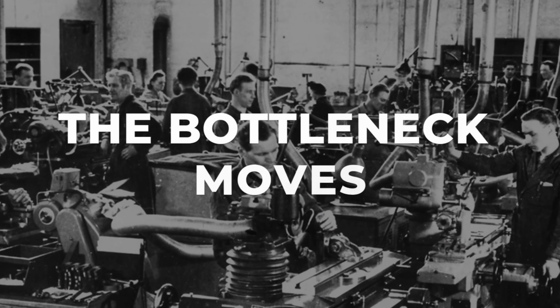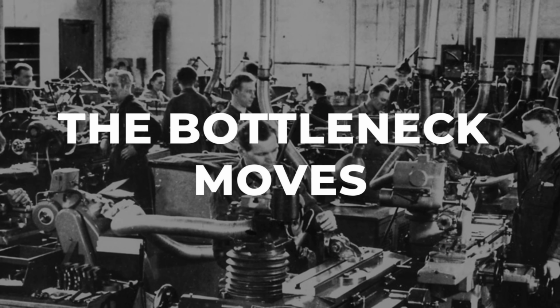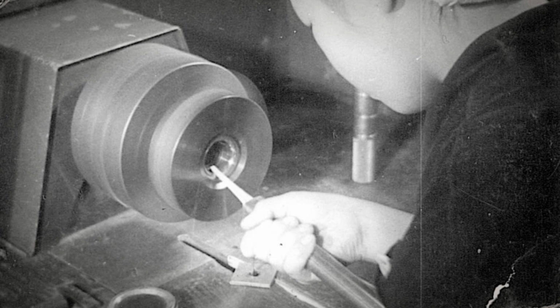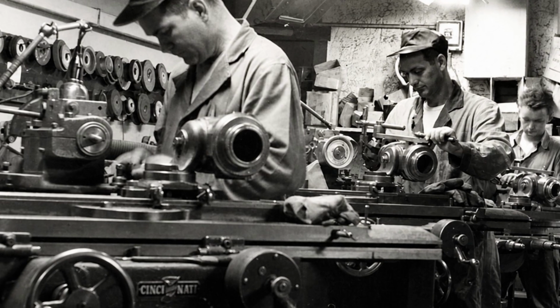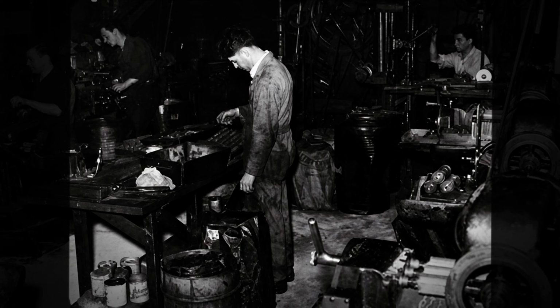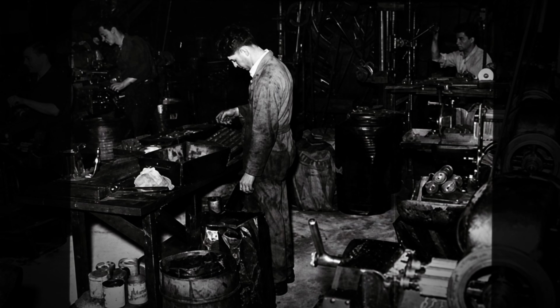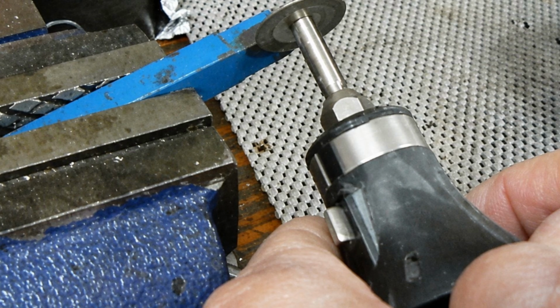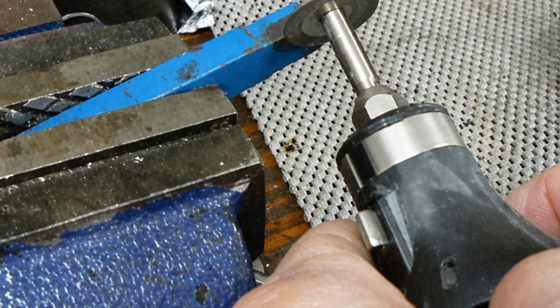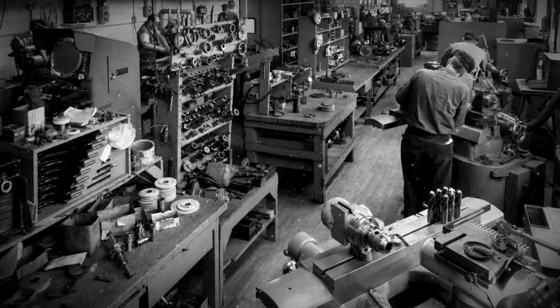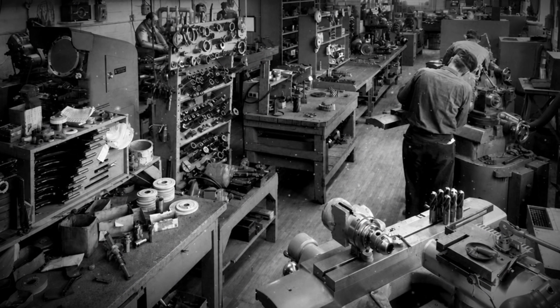By 1957, the material was no longer the bottleneck. The bottleneck was what shops did with it. The brazed tip economy had a rhythm. Braze a carbide sliver to a shank, grind the geometry, cut until it dulls, then grind it again, and again, until there is no tip left to grind.